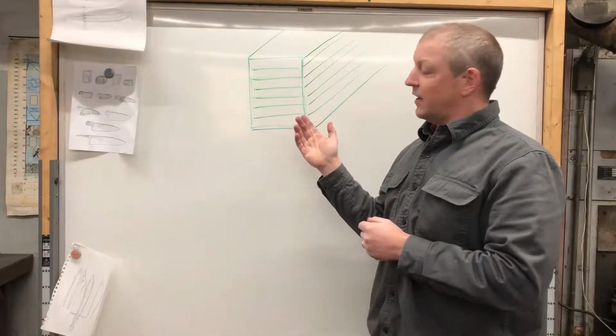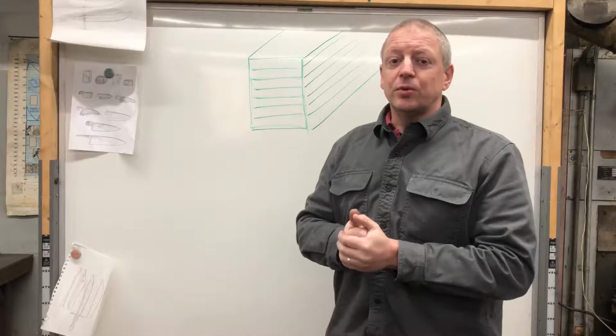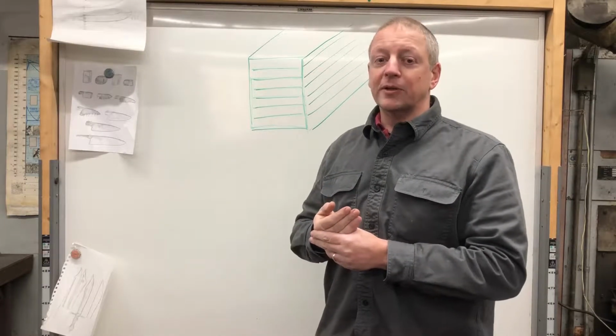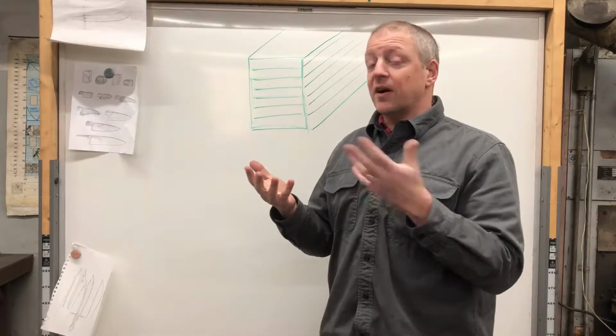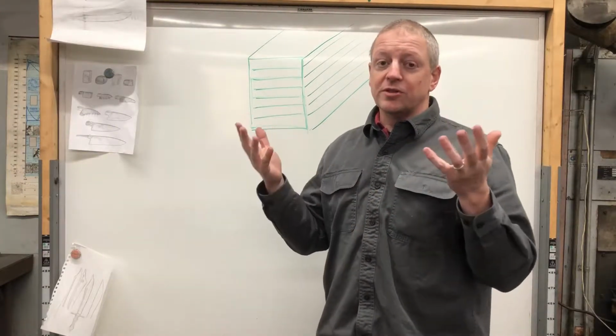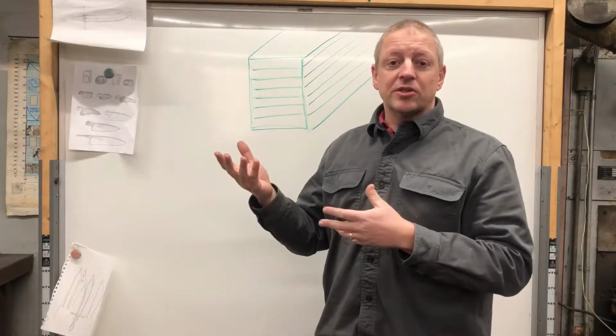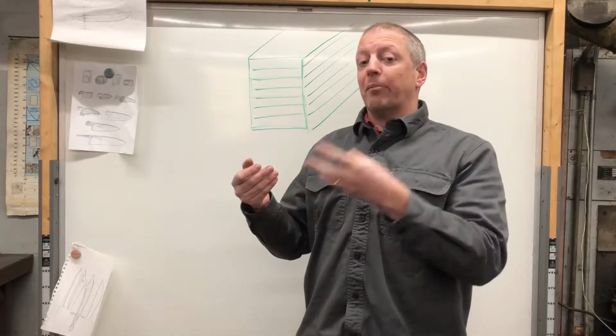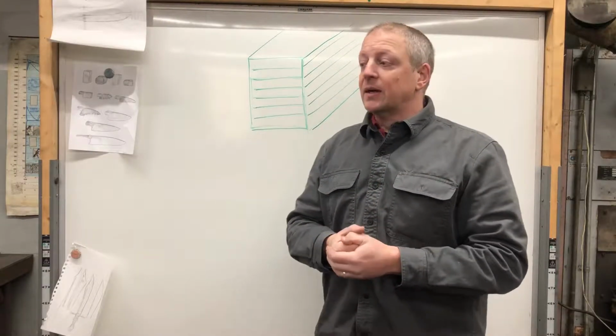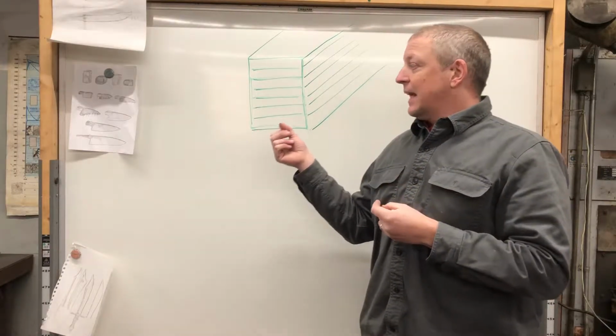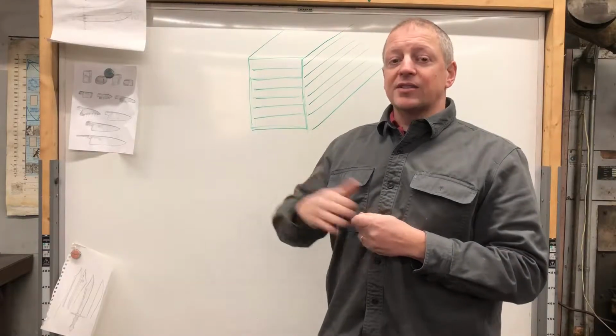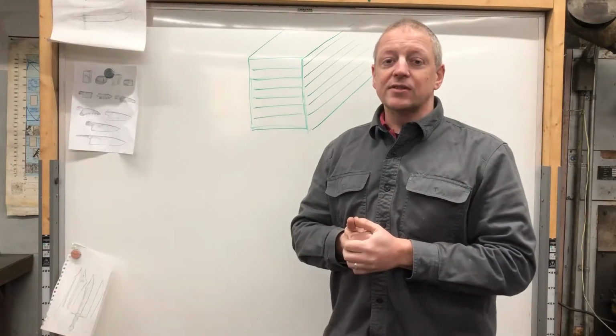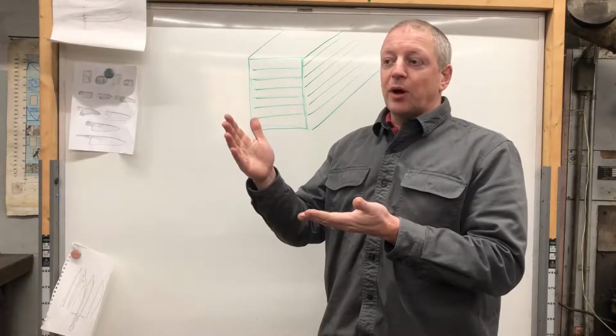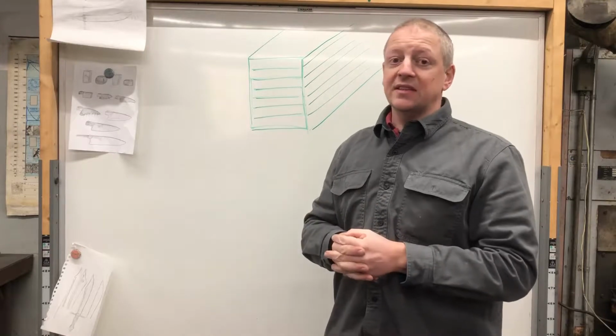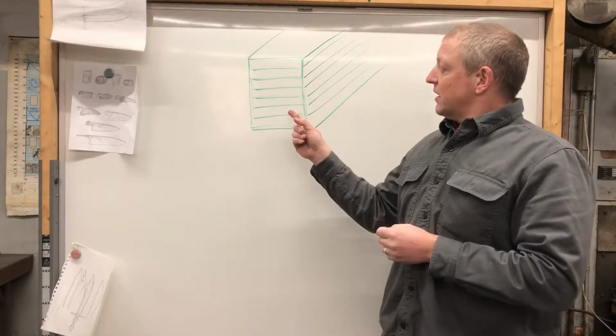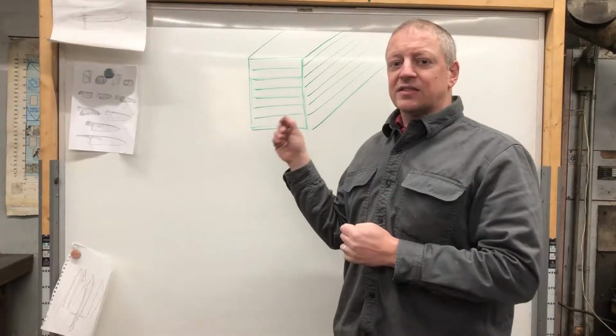So if any of you have done any jewelry work and you use flux on, say, copper, and the copper flux is very closely related to the flux we would use in forge welding. Copper flux is typically boric acid, whereas we are using borax. They're chemically pretty close, and they function in very similar ways. And it's not to say that they don't dissolve oxides. I think there's pretty good evidence. If you put borax onto a piece of steel, you can see it helps clean the steel. It does do that. However, that bubbling action is not the flux cleaning the steel.